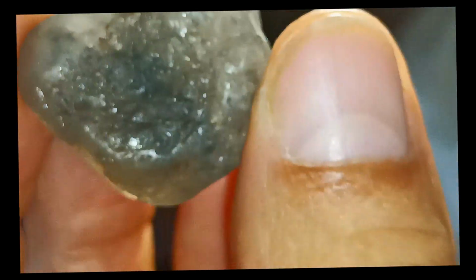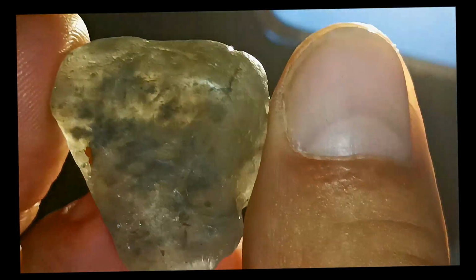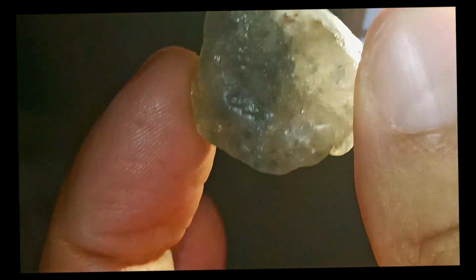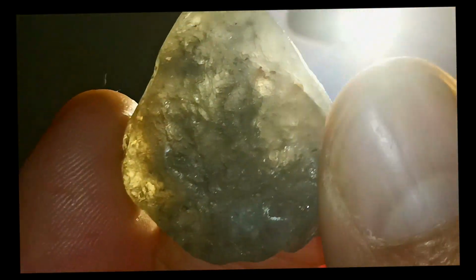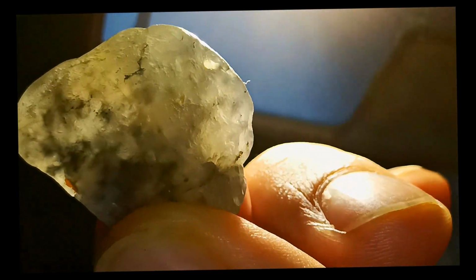Refraction of light is a fundamental element in crystal recognition, optics, and I am very attracted to the internal energy of light that a crystal actively emits when illuminated. Cubic stones are monorefractive, isotropic. Light passes through them as a single ray, meaning they have only one index of refraction and no birefringence. Hexagonal stones are birefringent, anisotropic. They split light into two rays, which can be observed with a gemological polariscope or refractometer.